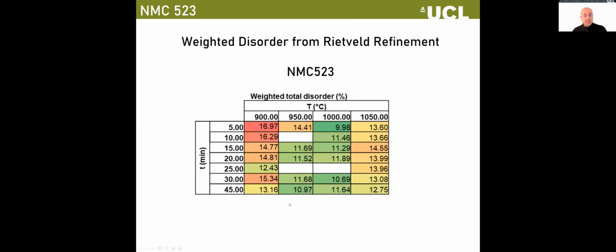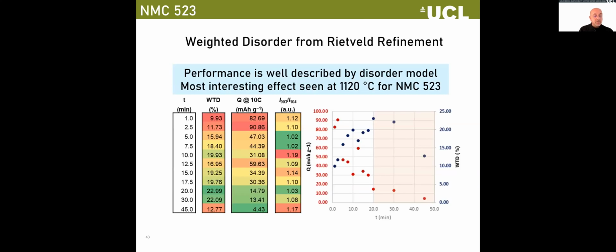So anyway, just to finish this story off, what we're seeing here during these times and temperatures is much, much higher than you would expect for a good performing cathode. And this is what the whole of the literature is pretty much saying, with a few exceptions. So I'm going to talk you through what we've observed. And this is for NMC 523. So this will be 50% nickel, manganese 20%, 30% cobalt. And this is, again, one of the interesting cathode materials that people are very focused on. The 622 as well are very much of interest for automotive, as well as the 811.